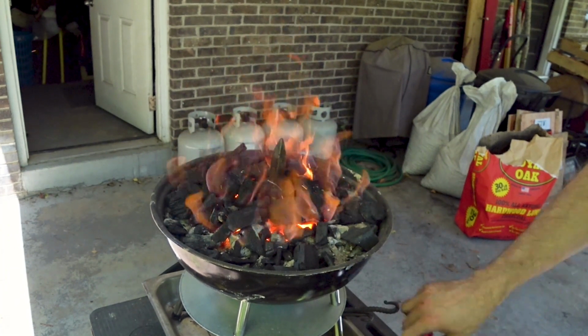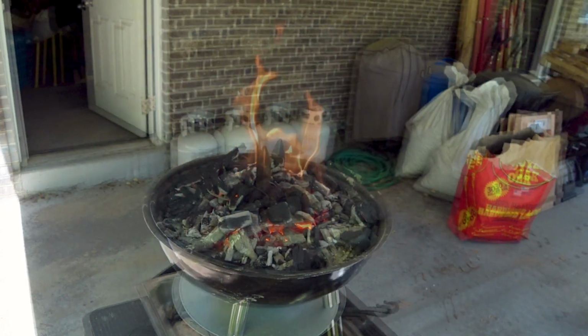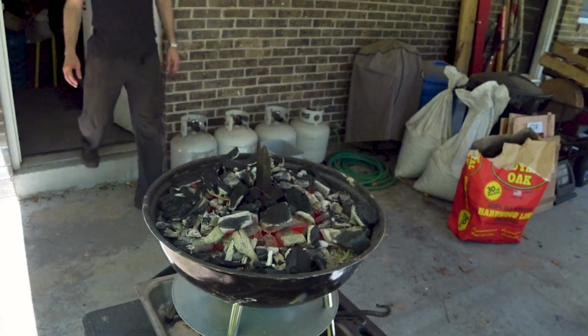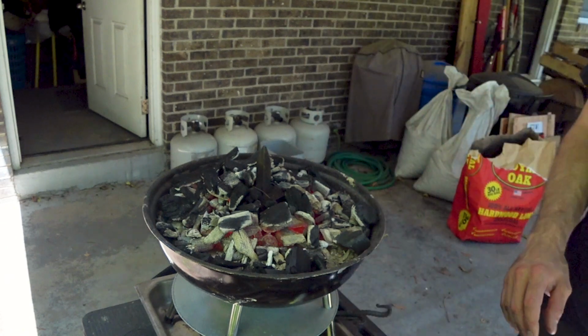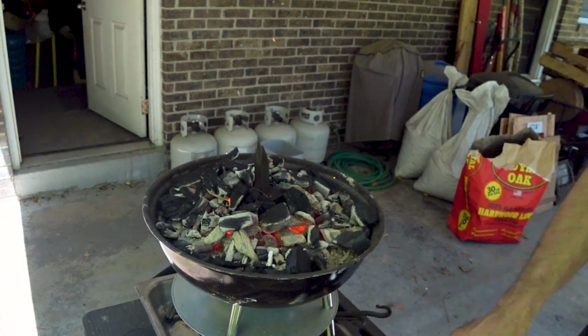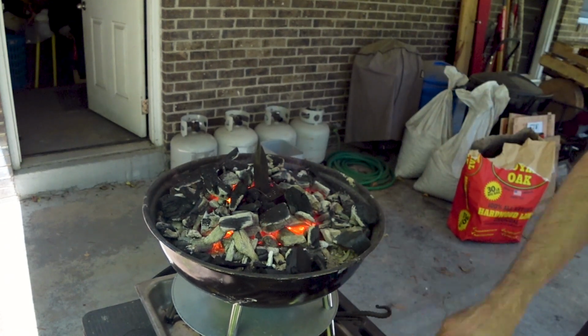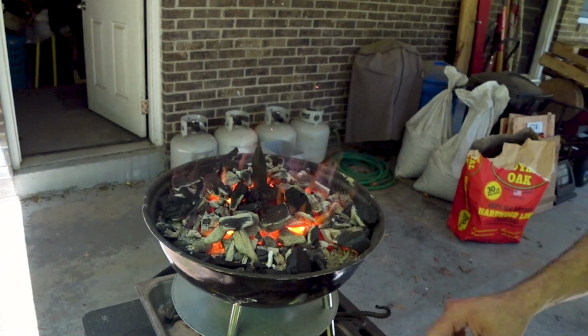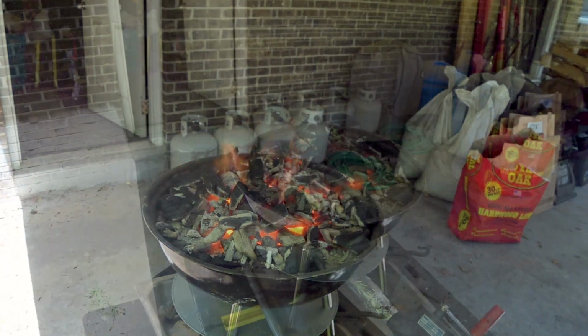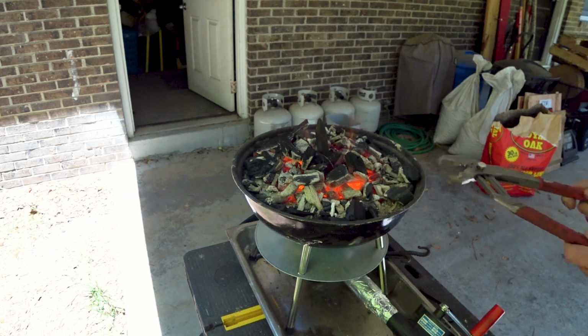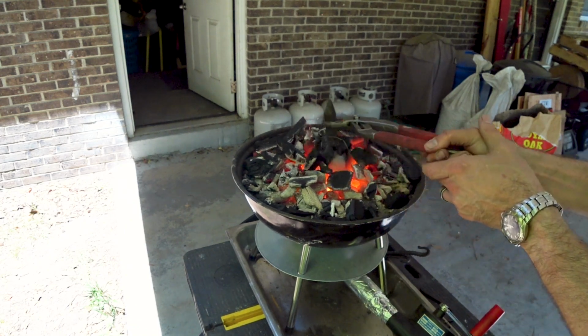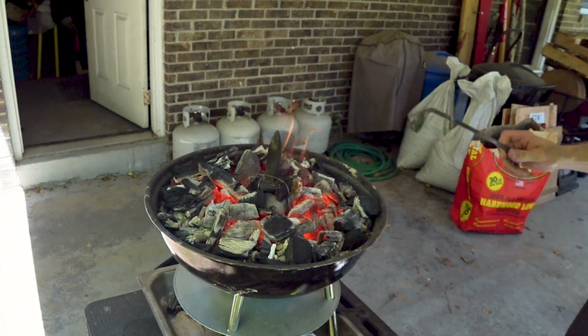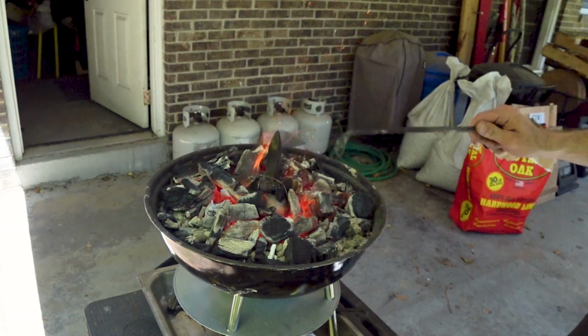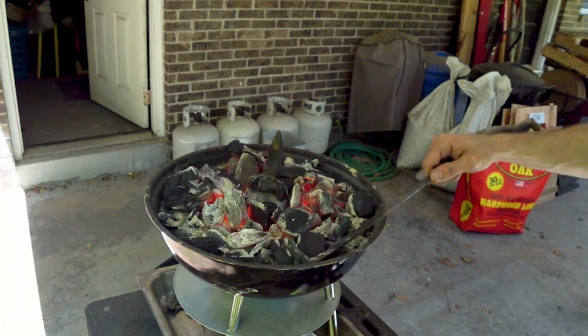The case hardening process is both time and temperature dependent, so once you get the anvil up to temperature, you need to allow it to soak in the heat for between 20 minutes and an hour in order to absorb the carbon. This should give you roughly a 1 millimeter thick case. The longer you soak at temperature, the deeper the case will become, but recall there's only about 3/8 of an inch of carbon compound surrounding that anvil, so we need to remove it before we burn through it, otherwise we could ruin the whole process.